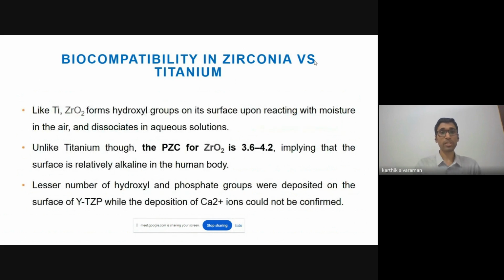So how does zirconium dioxide fare in comparison to titanium? Like titanium, they do form hydroxyl groups on the surface upon reacting with moisture in the air and dissociate in aqueous solutions. However, unlike titanium, the PZC for zirconium dioxide is 3.6 to 4.2, implying that the surface is relatively alkaline in the human body. Importantly, a lesser number of hydroxyl and phosphate groups were deposited on the surface of the yttrium stabilized tetragonal zirconium, while the deposition of calcium ions could not be confirmed.